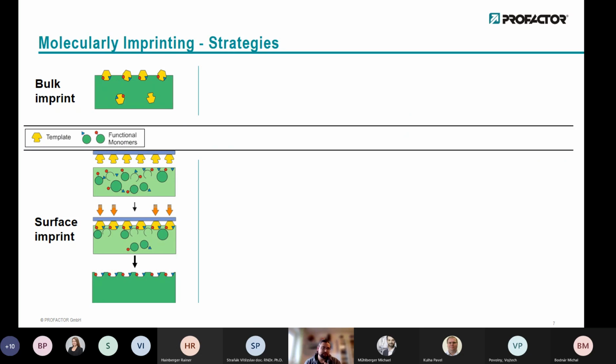You can separate this, how to practically generate MIPs, in two ways. The first can be referred to as bulk imprint, one-step imprint. There are several names in literature, but what you actually do in bulk imprinting is mix everything together, let it polymerize and extract afterwards. So that's really straightforward. So basically what you do is introducing the analyte into a monomeric solution, let it polymerize by itself and extract it afterwards. More controllable is a surface imprint where you just use a template that's immobilized on a stamp, imprint into it and cross-link or cure it during the process, so you have exclusively the binding sites on the surface.